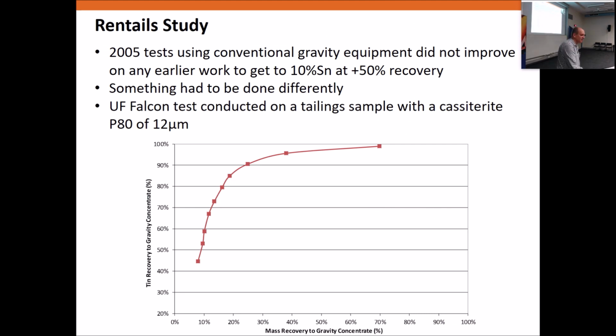So we had a major rethink in early 2006. There was a particularly poor set of results from some fairly standard gravity test work, and that had got nowhere near our stretch target of over 50% tin recovery into a 10% tin product, which we considered suitable for downstream pyrometallurgical tin fuming. So really doing the same things again that have been tried since 1972. It's a first-class example of idiocy. You know, we really had to do something different.